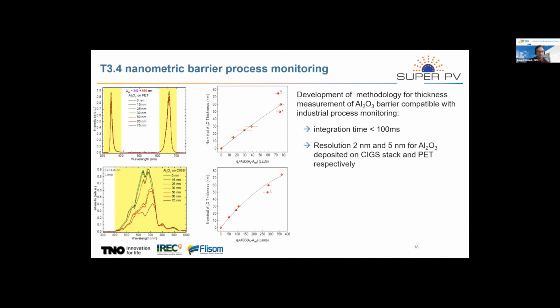And then we also have this monitoring provided by IREC for measuring the thickness of this PET or aluminum oxide layer. The measurement is based on reflection. Here we have two approaches, one using LED as a light source, with a light source at 340 and at 660 nanometers. You can see that the intensity of this peak varies with increasing aluminum oxide layer thickness. From this intensity peak, you can then derive the nominal thickness as a function of a quality factor, which is derived from this measurement, as IREC calls it. This gives you an idea of what the thickness of your aluminum oxide layer on your PET is.